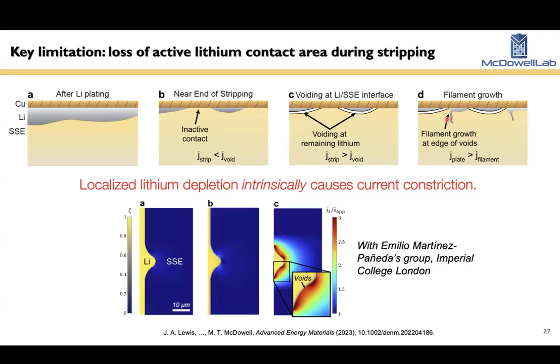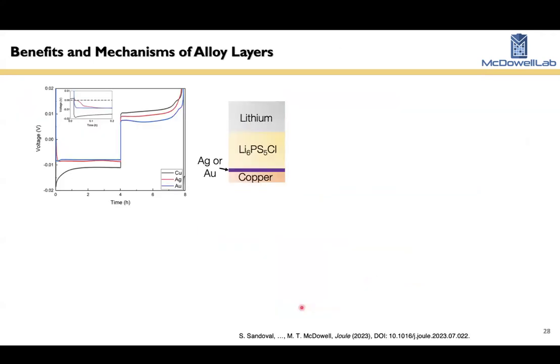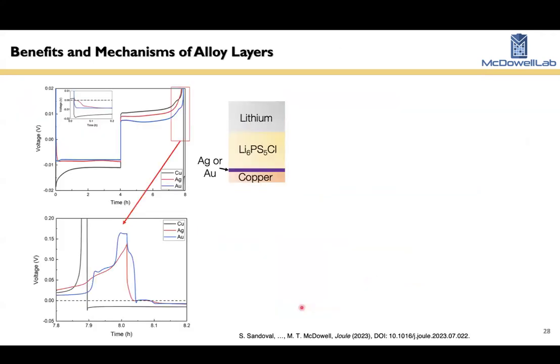So basically it's this kind of necessity of not having completely atomically uniform stripped lithium that will cause these filaments to grow. So there's some electrochemical evidence for this as well, and modeling evidence. This is modeling from a colleague's group at Imperial College London in the UK, showing that voiding can happen in this phase field model if you have this kind of protrusion, or this simulates a lithium island. So this is a problem.